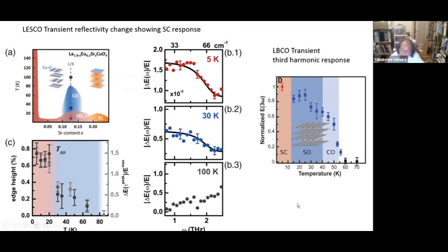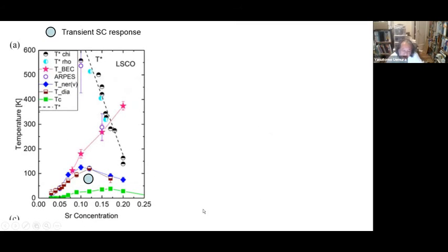So if we assume that the carrier density of these systems is more or less the same as the 0.125 carrier density in LSCO, then we can plot the onset of this transient effect, and it comes something like here. I think this depends very much on the power of the laser and various details. So this should not necessarily be compared exactly to the Nernst onset or this line, but I think it is probably telling us that this transient phenomenon is setting in along this line, and not with the very high temperature of the T star line.